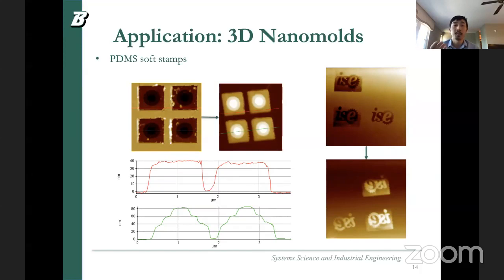We can use a PDMS stamp. So we have a stamp, we can easily stamp them in a parallel way. So this is one example, and it shows it can fabricate PDMS in a reverse way. And I also attached a few other examples here. This is a logo made using AFM-based nanomachining on the PMMA surface, of course. And it has different depths, showing different Z height features. So doing the same thing, we use the PDMS soft stamp, soft material. We do the casting, and we fabricate the reverse geometry like this. As you can see clearly, different Z heights with clear resolution can be reversely fabricated.